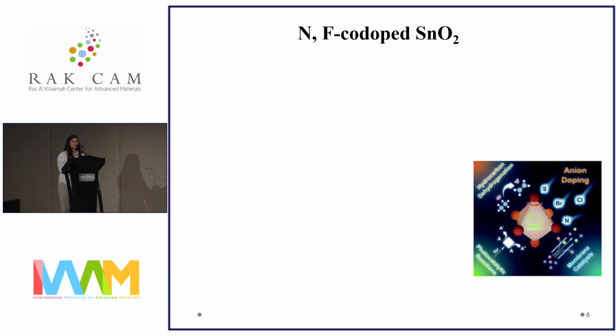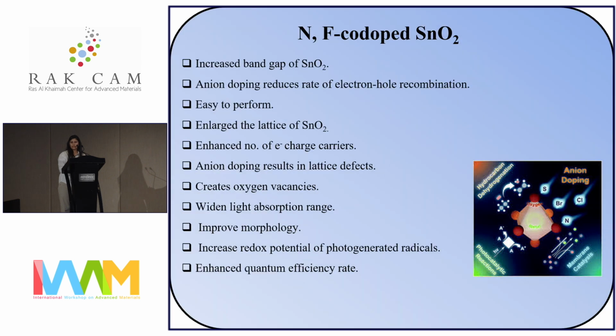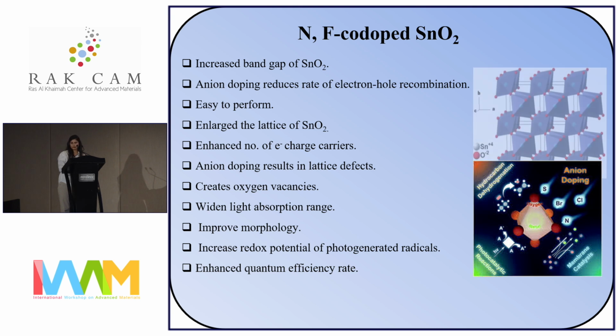In my work, I have preferred to choose anion co-doping of SnO2 because anion doping was increasing its band gap, that is, the band gap absorption range was widened to absorb more of the visible light from the spectrum. It was quite easy to perform. It enlarged its lattice, which was causing disorderness and charge imbalance in the lattice of SnO2, due to which oxygen vacancies were created, which is an essential requirement in this photocatalytic hydrogen generation process.